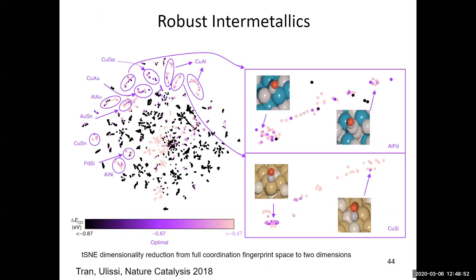Okay, so we took all of these materials. We tried to find the groupings that were most likely to be interesting. So this is a really simple t-SNE visualization, trying to cluster based on composition. These islands, for example, these are two islands that are all copper aluminum. And we want things to be in the purple range. It's okay to be white. It's bad to be black.